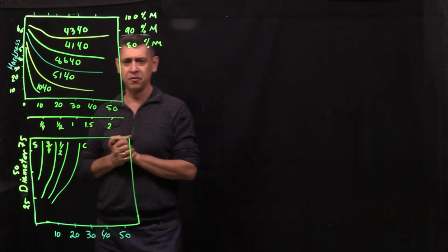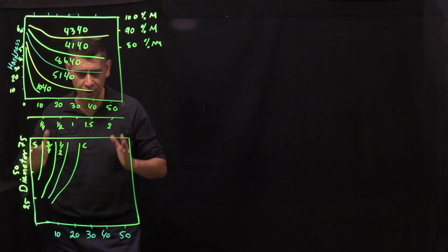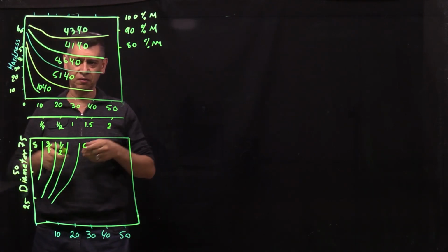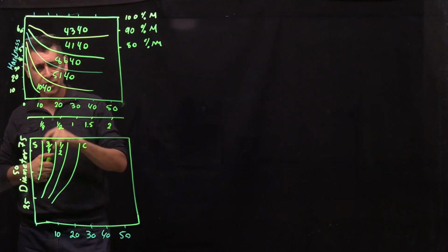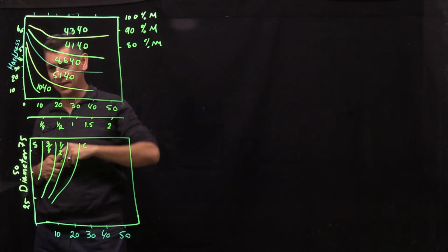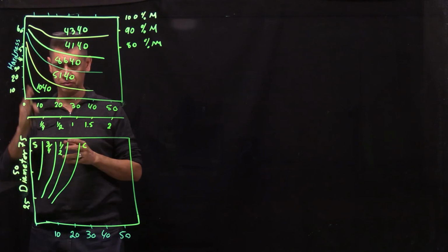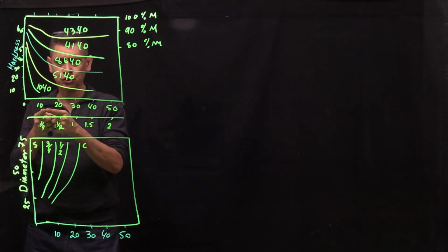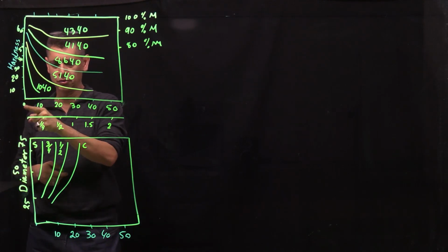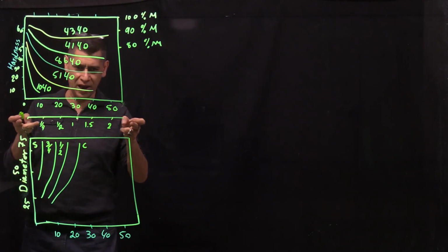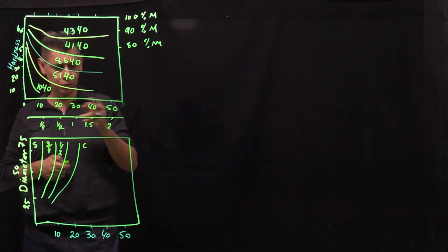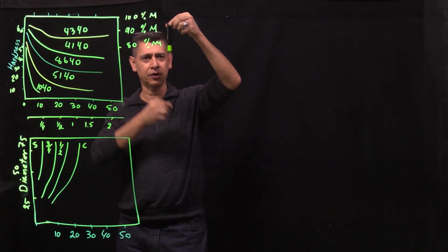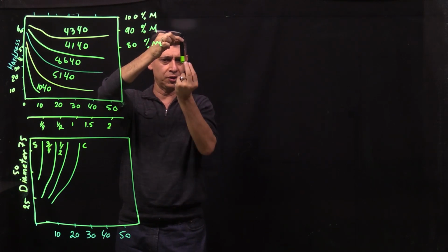First of all, let's get familiar with the two very common charts we are using. The first one is similar to whatever you've seen, obviously. This is the hardness, Rockwell C, could be other units, but usually they use Rockwell C, versus the Jominy distance from the head. So it's 0, 10, 20, 30, 40, 50, or you have the bottom one, which is inch, from 0 to 2 inches. Imagine that this is the Jominy rod, and you use it red hot, you put it there, and it's cooling down from this end.